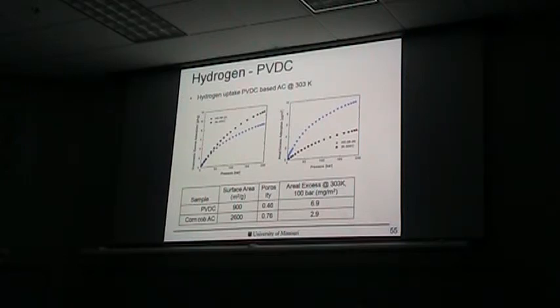If you look at these isotherms, you will think, okay, why do we do this? The activated carbon from corn cob stores more gas, so it's higher over here compared to this one. But if you take a closer look and normalize the uptake to the surface area, you will see that for lower surface area, the PVDC-based sample stores a lot more, almost twice as much gas, but it has a lower surface area, which is pretty interesting at this point.